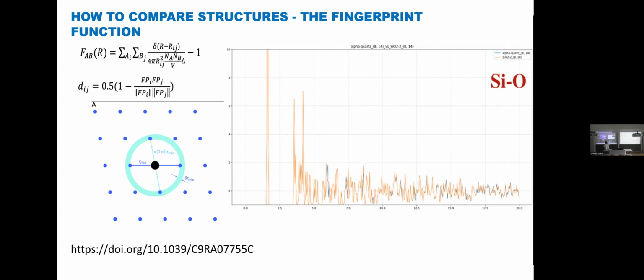And here you see some example. We start from silica, and then we look for oxygen atoms as neighboring atoms to silicon in some structure. And you see the closest number of atoms, then scaled atoms at another distance. So here is the distance in angstroms, and here is the number of atoms. And this function should be unique for each structure. That's why we can compare them. That's why it's called a fingerprint, because it's unique.